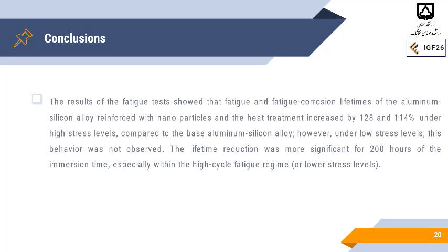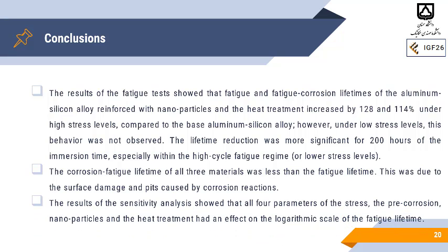So for the conclusion, I want to say that the results of the fatigue test indicated that the fatigue and corrosion fatigue lifetime of the aluminum reinforced with nanoparticle and also heat treatment increased about 128 and also 114% under high stress, compared to the base material. And for the lowest stress level, this behavior was not seen.